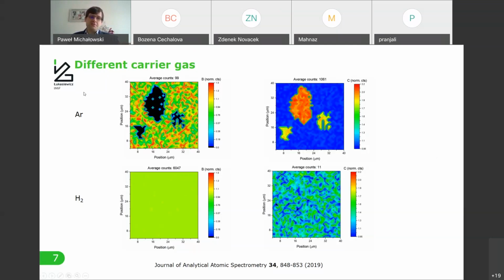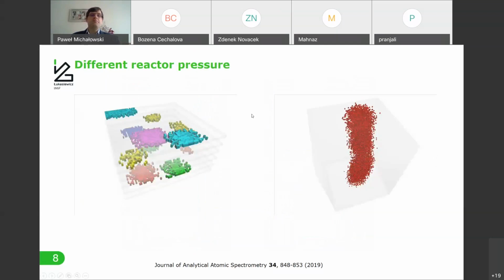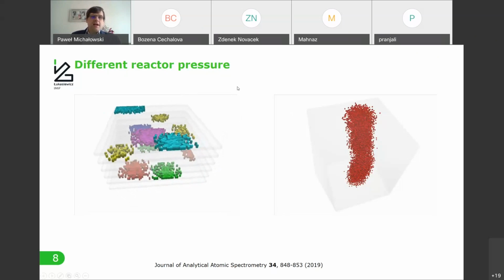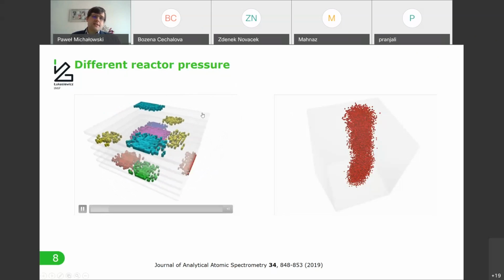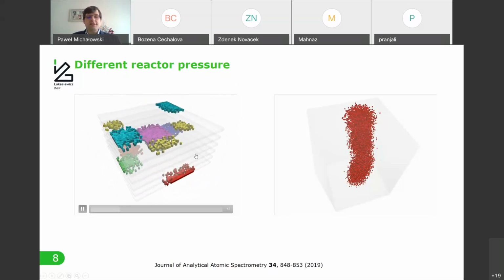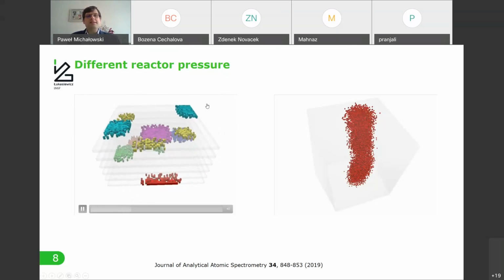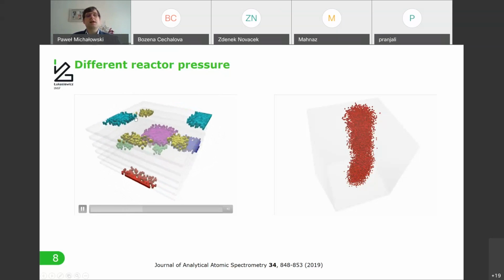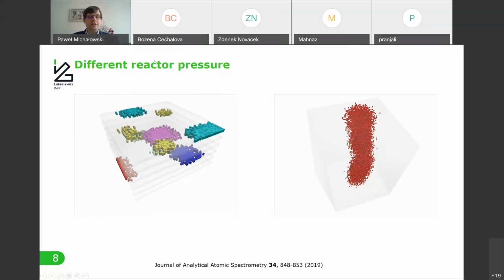So this time we switched to argon to see these precipitates, but we did it for different reactor pressures. When we did it for the high reactor pressure, this is the so-called self-terminated growth mode. You can only grow 6 layers of boron nitride in this mode. It is, as its name says, self-terminating after that. Nobody exactly knows why, but here is a very nice result: when we analyze these carbon precipitates, we can see some animation. As you can see, I mark with different colors the carbon precipitation present in different layers. There are exactly 6 layers, as you can see here. But as you can see, there is absolutely no correlation between the position of these carbon precipitates in one layer and in the other. So they are randomly distributed.